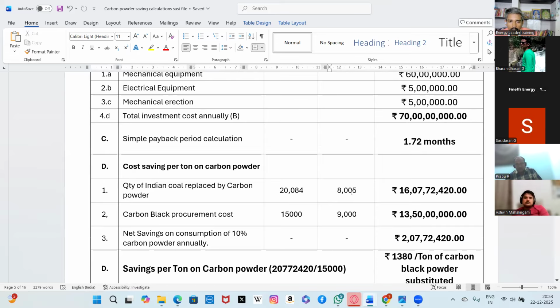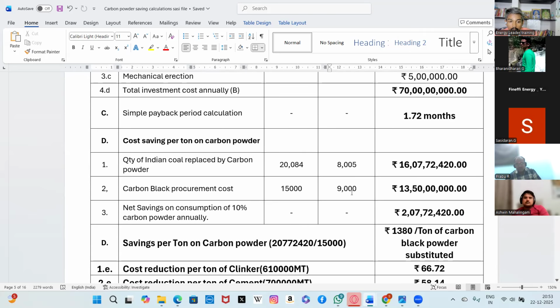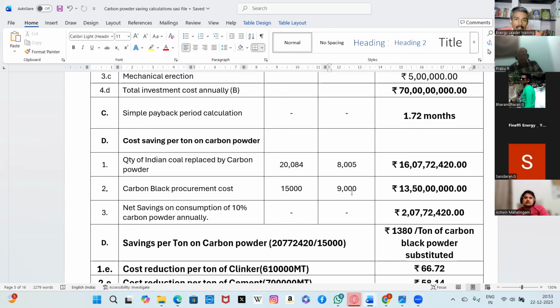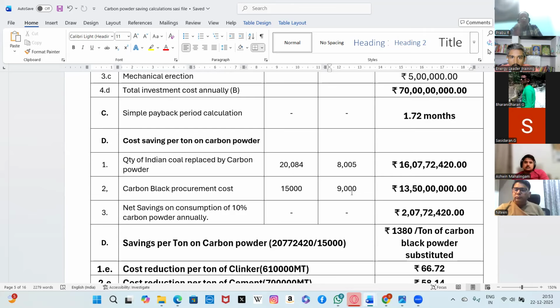Another thing is the saving per ton of carbon powder. If I use 1 ton of carbon, how much cost is saved compared with Indian coal? The cost of Indian coal, 20,000 metric ton, comes around 16 crores, and for carbon black, the same 15,000 at a rate of 9,000 comes around 13 crores. The difference is a saving of 2 crores, and this is only for 10%. If I divide it by the carbon powder, I'm saving nearly 1,380 rupees per ton of carbon powder. This is also an added advantage for me.